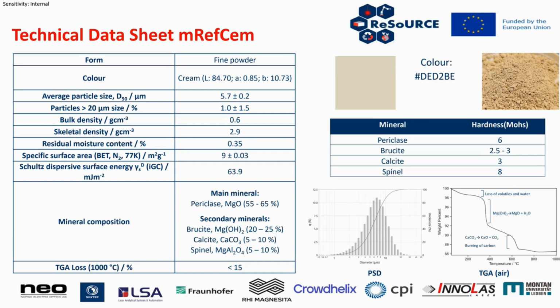And so, like residual moisture content. These materials pick up a slight amount of moisture on sitting, about 0.35%. And at 1,000 degrees Celsius on TGA, they lose about 15% of the mass from different compounds. So the loss of water from the magnesium hydroxide into the magnesium oxide again, and loss of carbon dioxide from the calcium carbonates. So that is the mRefCem.